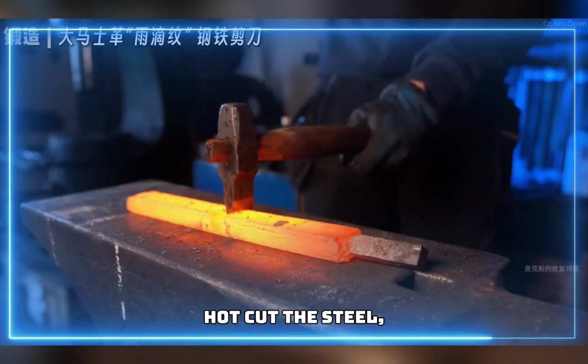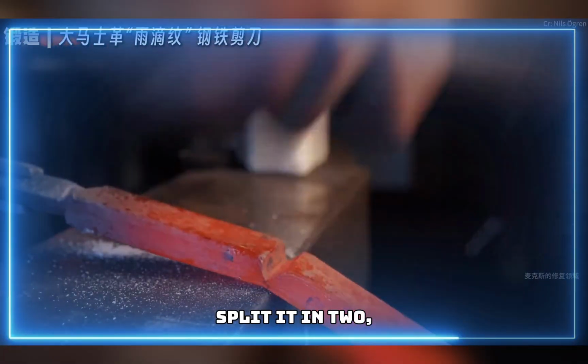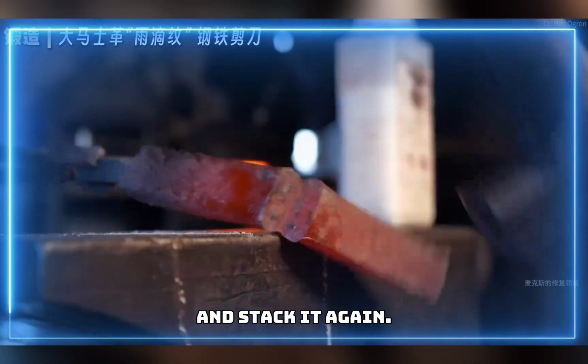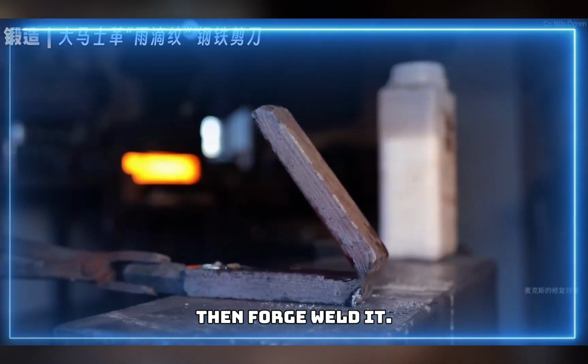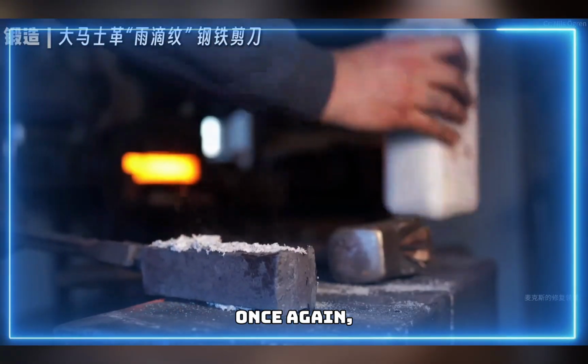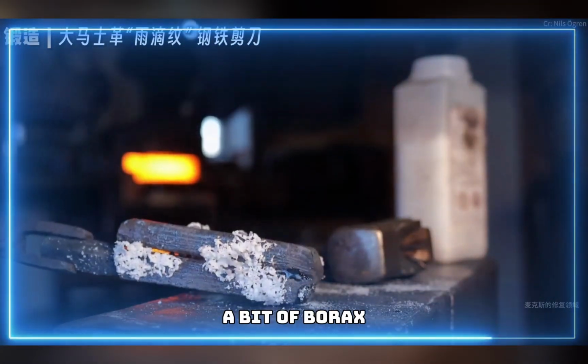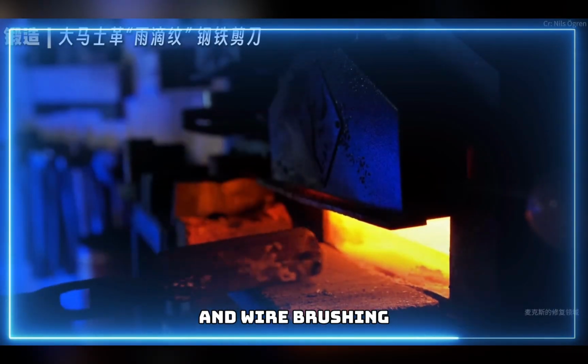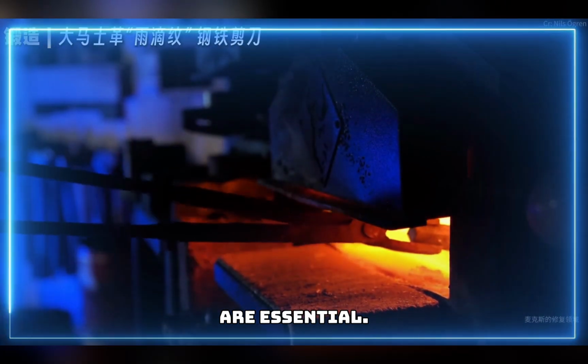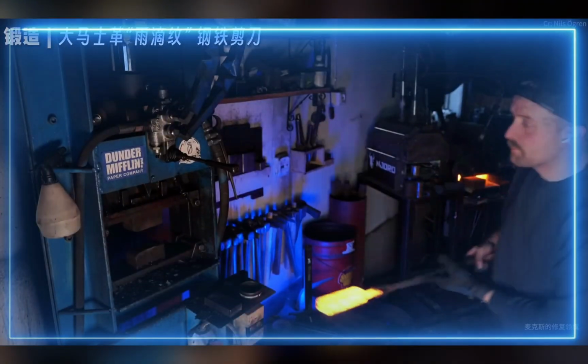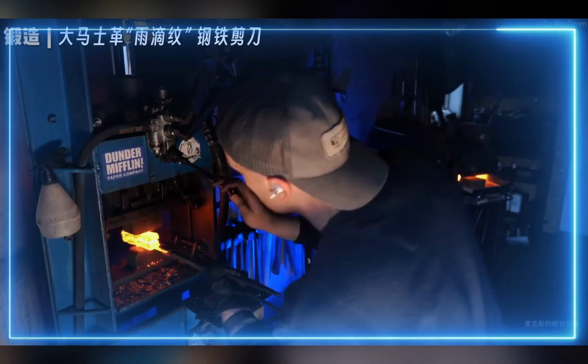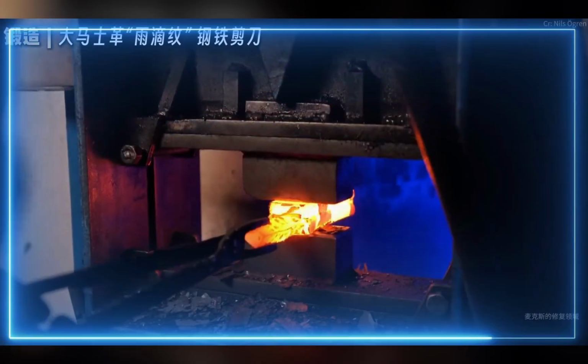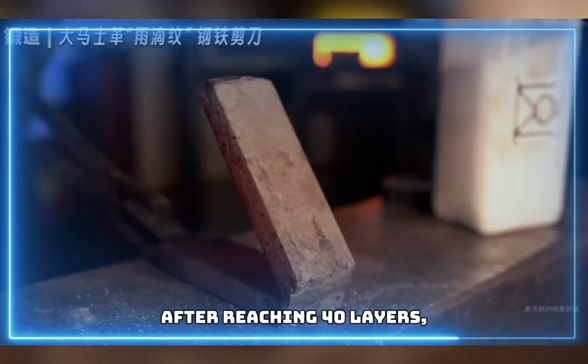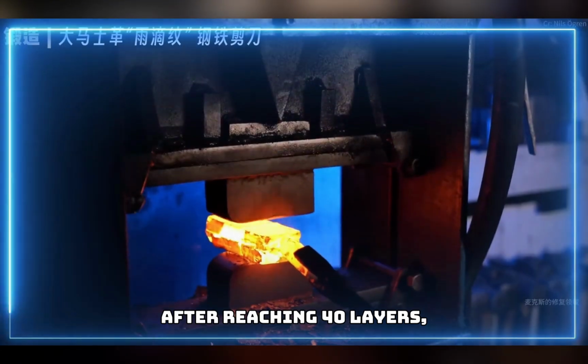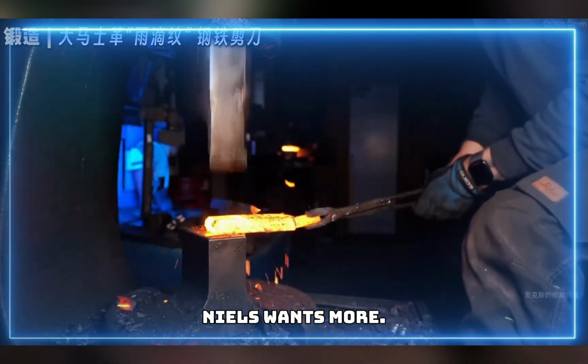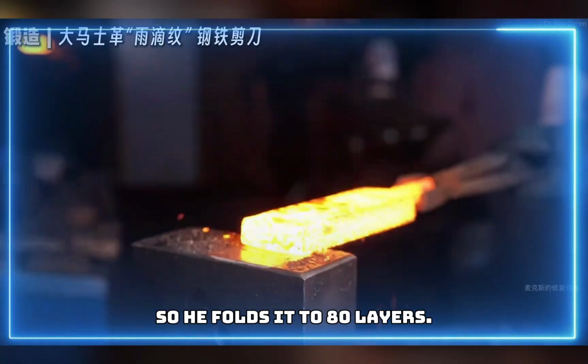Hot cut the steel, split it in 2, and stack it again. Then forge weld it. Once again, for good quality, a bit of borax and wire brushing are essential. After reaching 40 layers, Niels wants more, so he folds it to 80 layers.